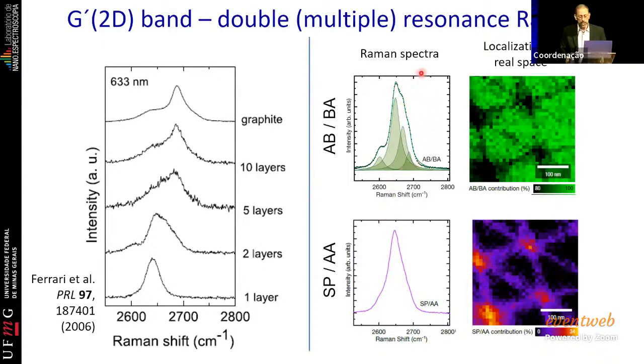And if you now image where you see such a shape and where you see such a shape, you see that this is exactly at the triangular areas where the graphene rotated back to the equilibrium situation of AB stacking. So this, I would say, is experimental evidence for what we expected to happen. And if you look now at the regions where we have this strain between the domain walls, you have this strange shape that is related more to uncoupled layers. Okay.